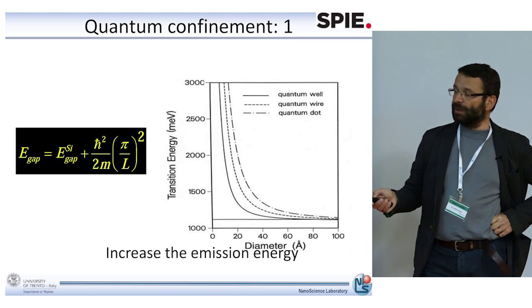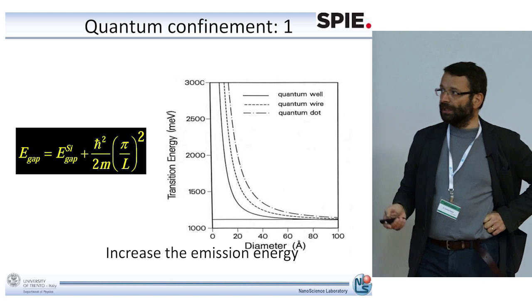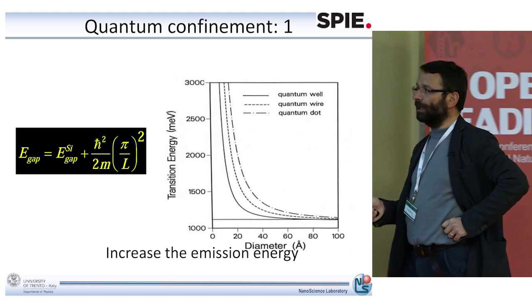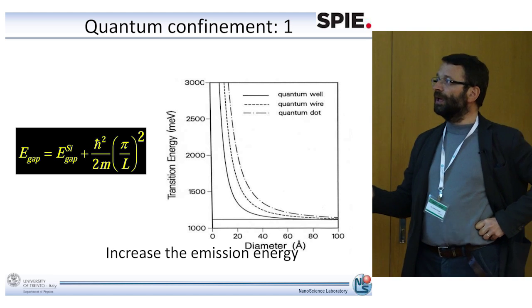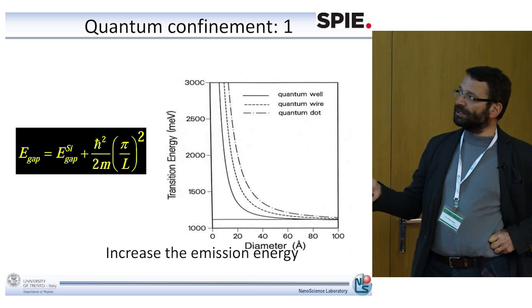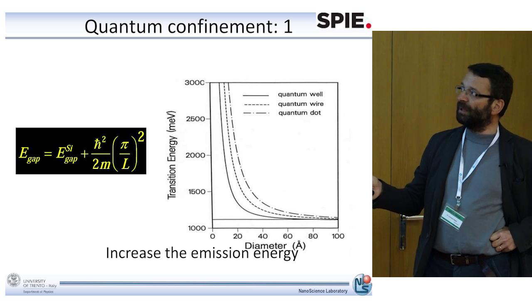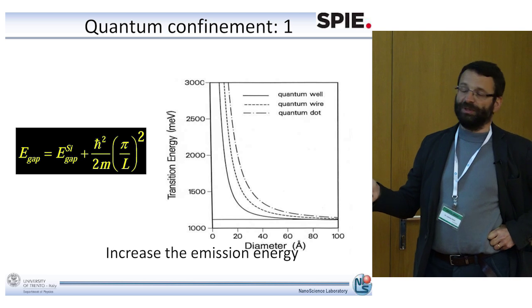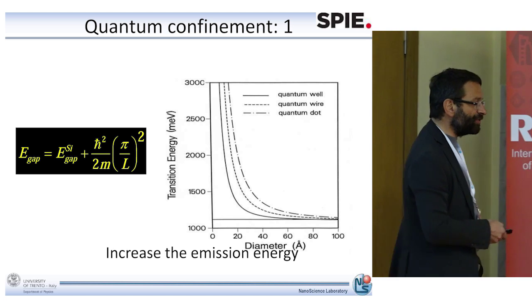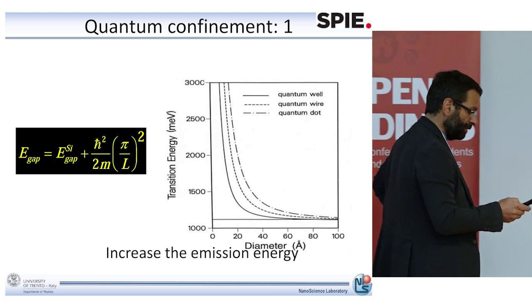You see that when we enter the low, few nanometer region, the band gap increases, so you have a widening of the band gap, and then you drive the band gap into the visible range. So this is the first consequence of quantum confinement.